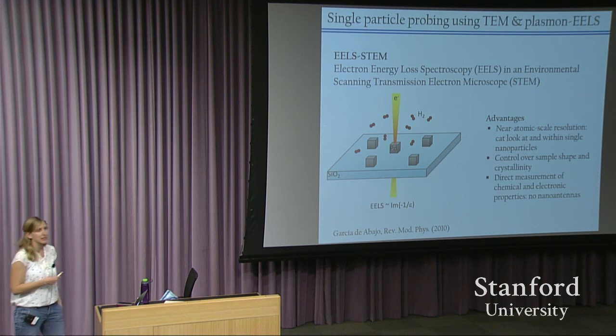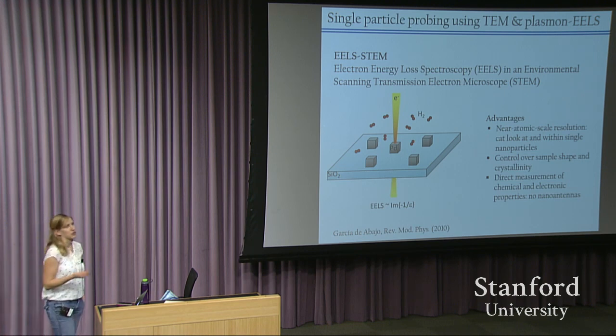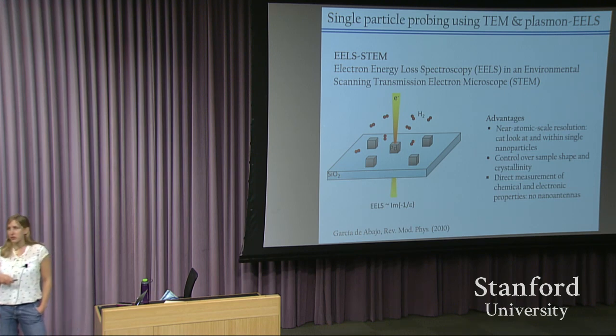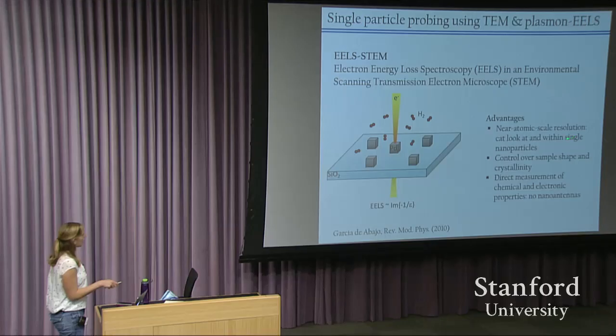Advantages of using this technique are many, but I'd say one huge advantage is that we have near atomic scale resolution. In the electron microscope, there's an imaging spatial resolution of 0.07 nanometers, sub-angstrom. So we can look both at and within single nanoparticles.